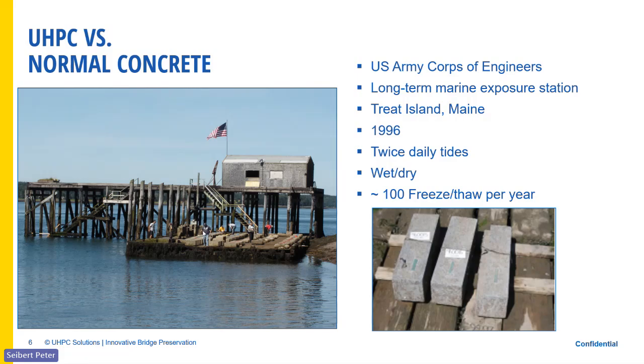So there have been samples out there now. And generally speaking, if you look at these samples after 20 years, you see chlorides penetrating the first quarter inch, and then it's dense. Nothing goes into the matrix. So making this material very durable.